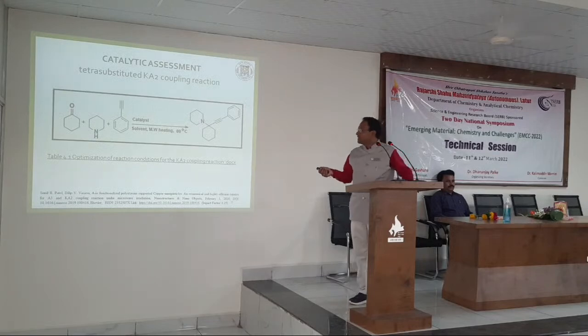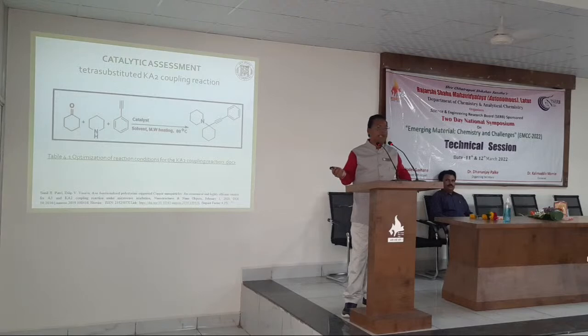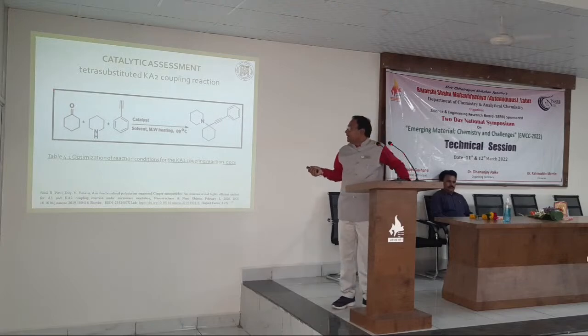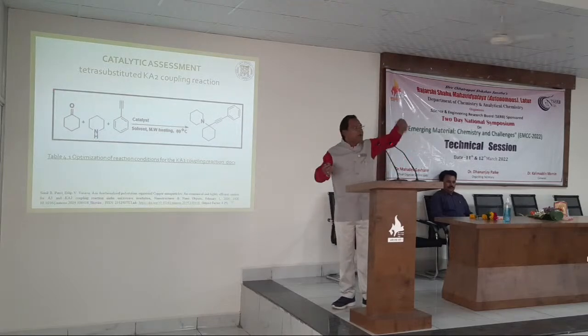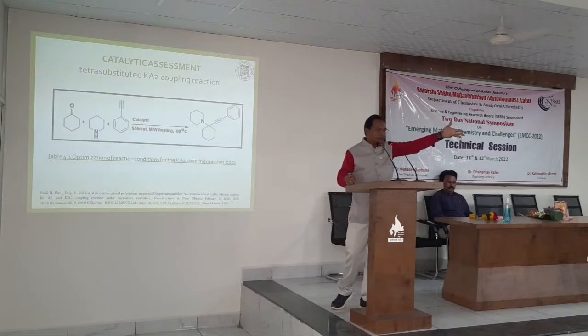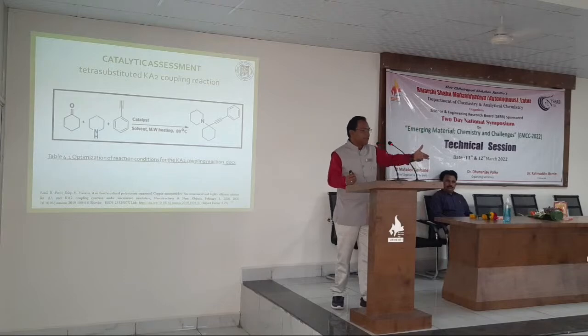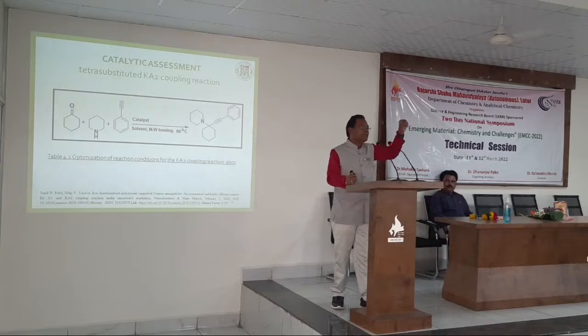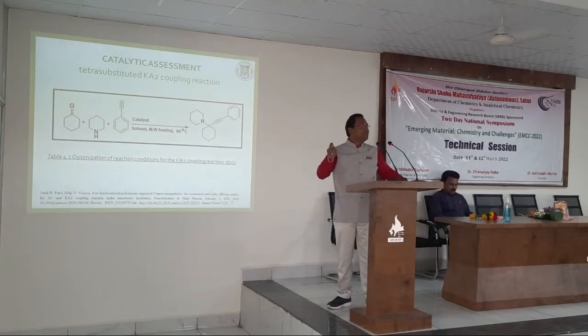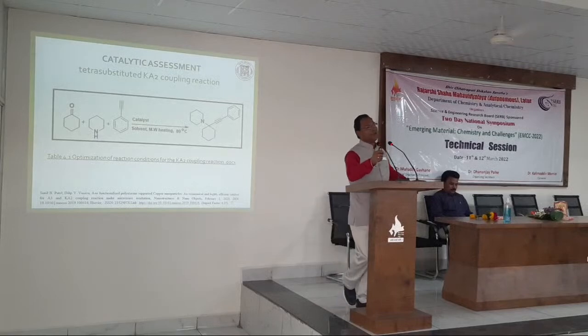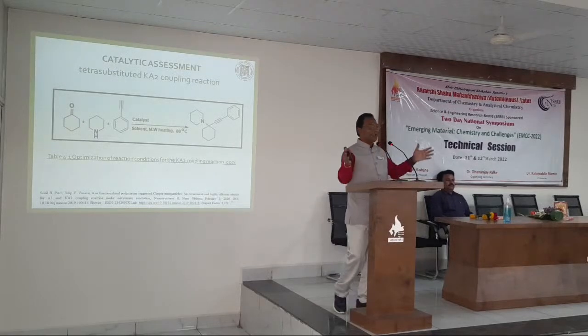So in that, this is the ketone, and this is the amine and acetylene. So that is why it is said KA2: K stands for ketone, A for the amine, and another one is the acetylene. This is the reaction reported earlier by the conventional method. We have reported the same method by using the nanoparticles. The original reaction took around 40 hours to prepare this compound, and with the help of the radiation we have completed it within 2 hours. So the time frame is decreased.